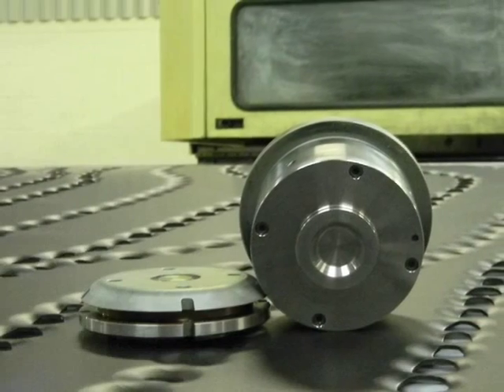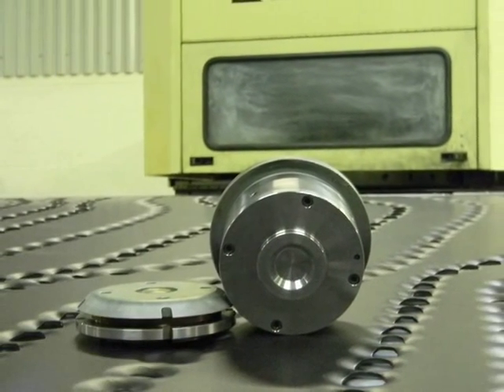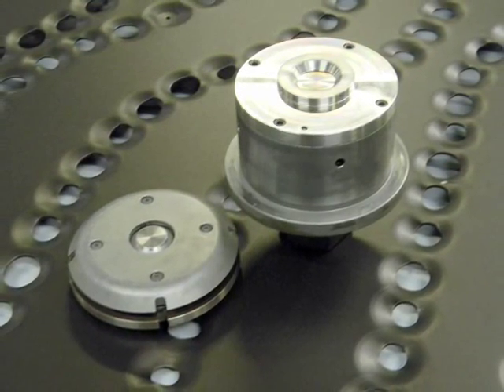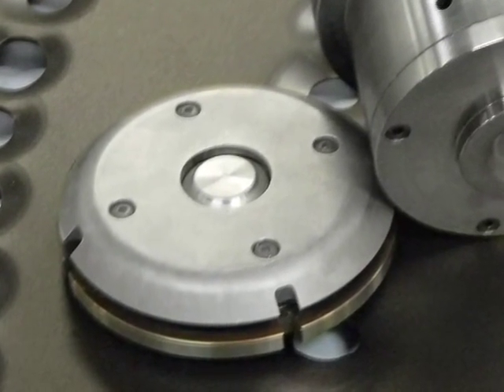The holder assembly shown here is hardened and ground to reduce turret wear. Mate's tooling design utilizes 4150 steel with a hardness of 38-42 Rockwell C to reduce friction and helps optimize the tool stripping force critical to making the hole dimples.